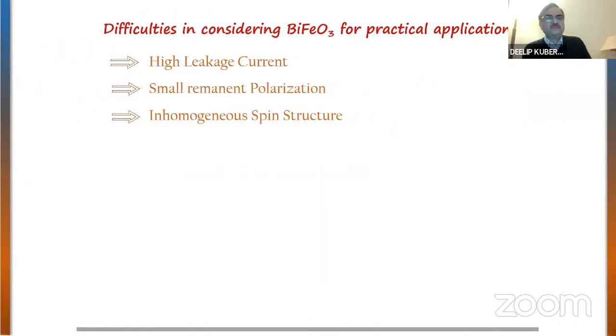But when you want to use it for some application in a device, there are difficulties. Difficulties actually come across when you use these for practical applications, because these BiFeO3 materials have very high leakage currents. They have small remnant polarization, which is not very good for the application basically. Remnant polarization means when you switch off the electrical field, whatever polarization remains in the material. And then they have an inhomogeneous spin structure. So this restricts the applicability of BiFeO3 and its derivatives or the substituted BiFeO3.